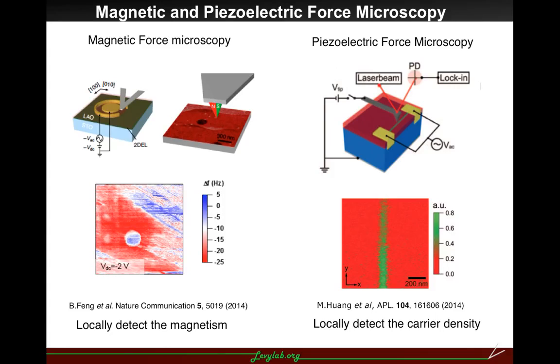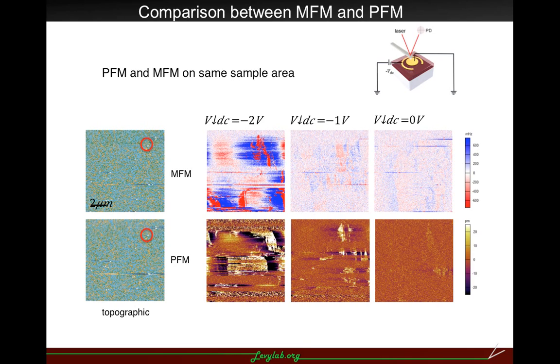While doing the MFM, the tip is kept at a constant height above the sample surface, and the tip is affected by the long-range magnetic force. So in this way, it provides a method to locally detect the magnetism. While doing the PFM, the tip is engaged with the sample surface, and it can locally detect the carrier density. Since we can do both PFM and MFM, it provides a way to study whether the magnetism is carrier density related. So we performed the PFM and MFM on the same sample area.